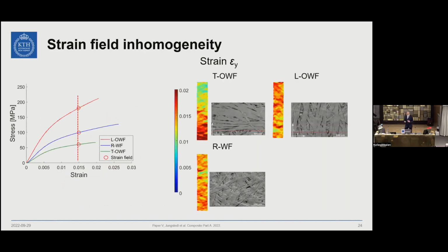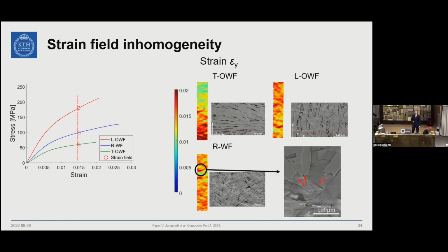Now, we can also use the strain fields to check the inhomogeneity in this type of material. If we take strain field plots from the same average strain, we can see that there's a lot of inhomogeneity in the strain fields. If we look specifically at those very dark red regions, which are the regions where it will actually fail later, you can see that there is a fracture of the fibers on the surface. So we have weak regions which fail, and these are the main reasons why we have this kind of nonlinear behavior of this type of material.